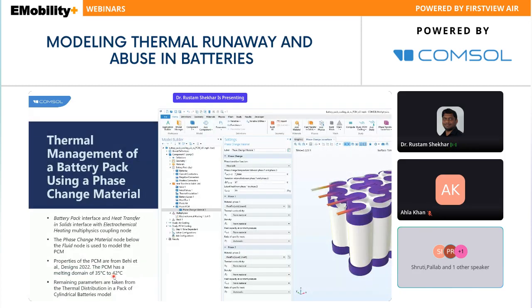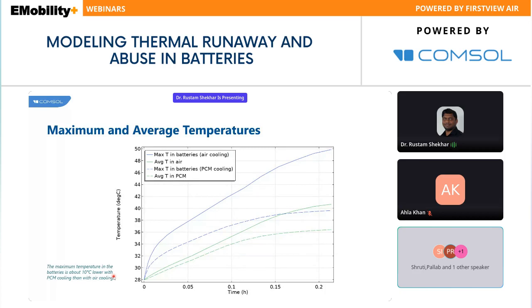Now, when you compare both cooling strategies, the air-cooled system and the PCM cooling, in the air-cooled system the maximum temperature is around 50 degrees Celsius, and with PCM cooling, or phase change cooling, the maximum temperature is around 40 degrees Celsius. So there is almost a 10-degree difference that you can observe due to the heating of the system. So we have two different strategies, air-cooled and PCM cooling, and PCM gives you a 10-degree lower temperature, which may help you prevent thermal runaway scenarios.